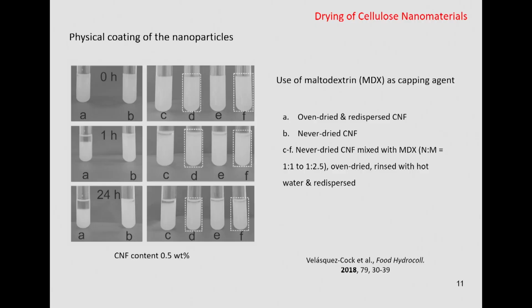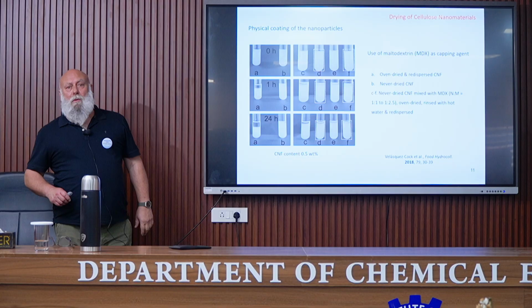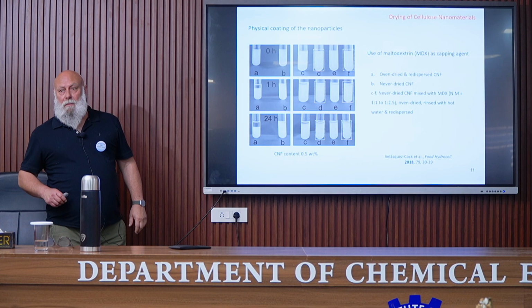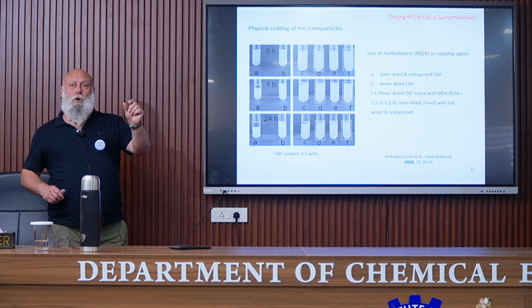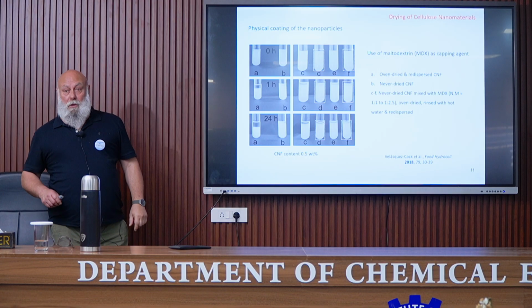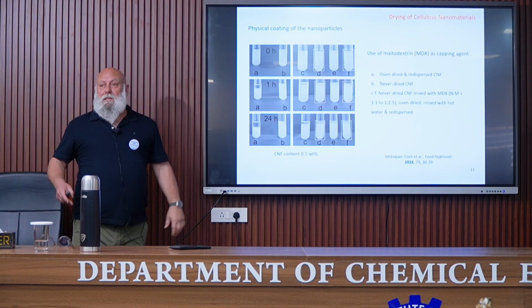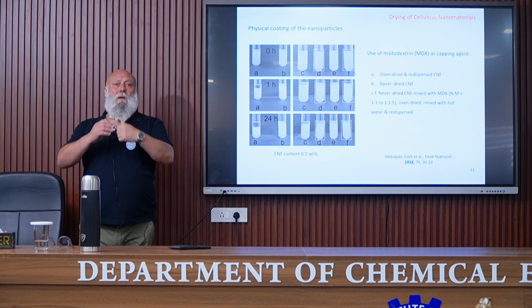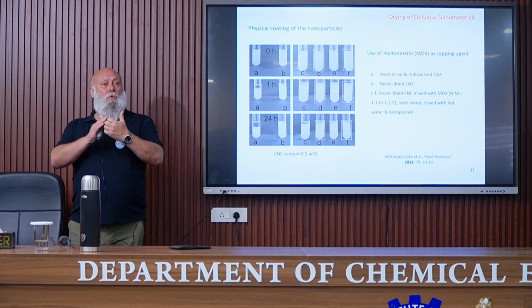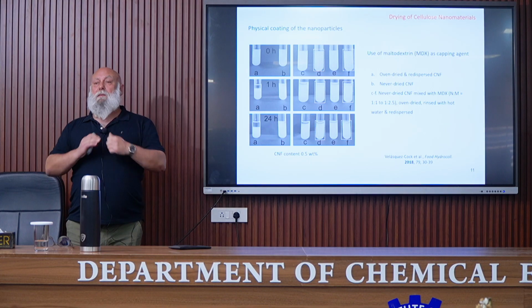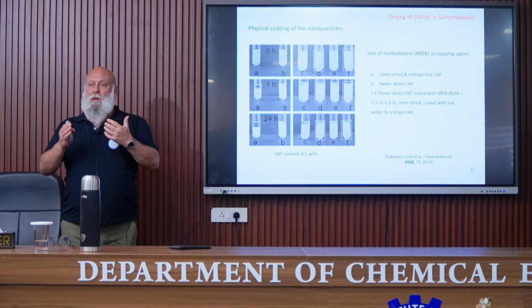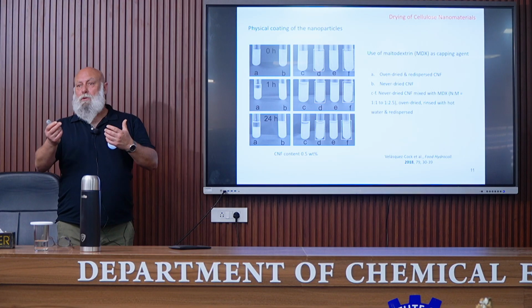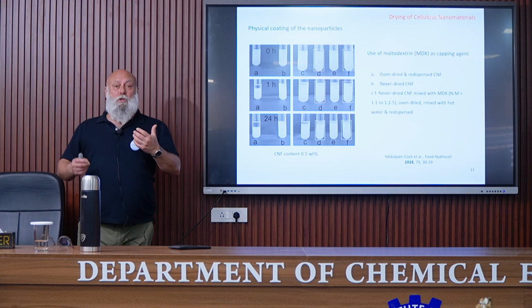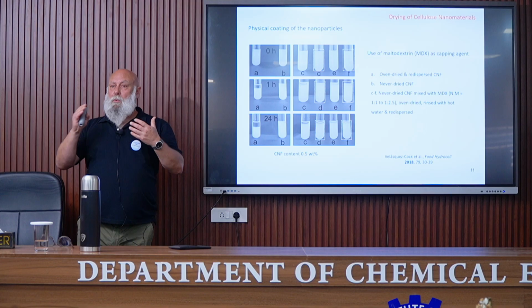I will show you some examples. So the first one is the physical coating of the nanoparticles. In this case, maltodextrin was used as a capping agent. Maltodextrin is a short molecular weight starch. And what was expected here is that this small molecule can have strong interactions with the surface of cellulose and avoid the aggregation. And then, because it's a low molecular weight starch, it can be just removed by rinsing the dispersion.